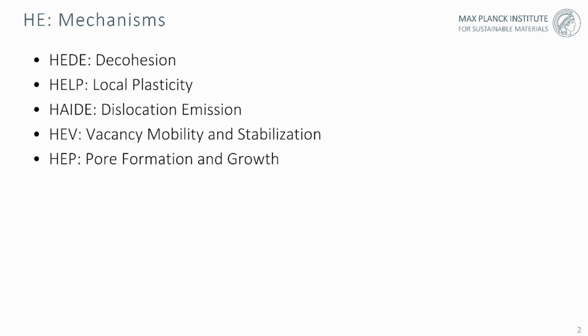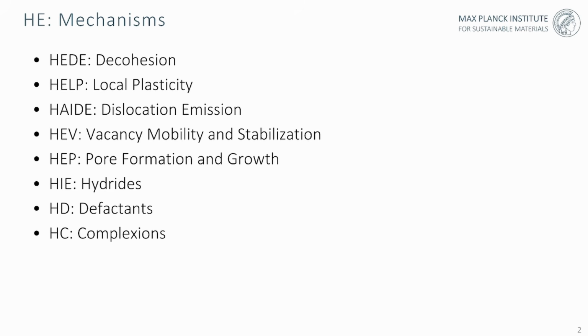Very often, under certain boundary conditions, you also can find pore formation and pore growth, which is accelerated when hydrogen is present. In some materials, for instance, particularly in titanium, zirconium, hafnium, etc., you can also form hydrides, which then can lead to embrittlement themselves, because hydrides are often very brittle constituents in such alloys. Generally, there's also defactant theory valid behind alloys that are loaded by hydrogen, and that means that according to the classical Gibbs adsorption isotherm, the energy of certain interfaces or defects can be lowered when hydrogen is present, and that can have an effect also on embrittlement.